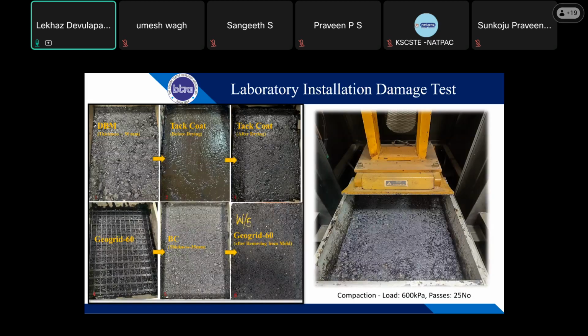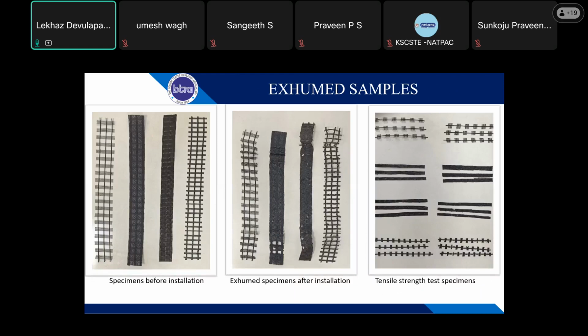For the sample preparation, with our slab compactor, we placed the geogrid in the same fashion. Here we kept the load constant at 600 kPa, and the number of passes for all the geogrids was 25. After that, we removed the sample from the mold, and then we split the two layers by placing it at 60° for 4 hours in an oven. We maintained a standard procedure so that it wouldn't affect the properties of the geogrid during exhumation or heating. And then we exhumed the specimens.